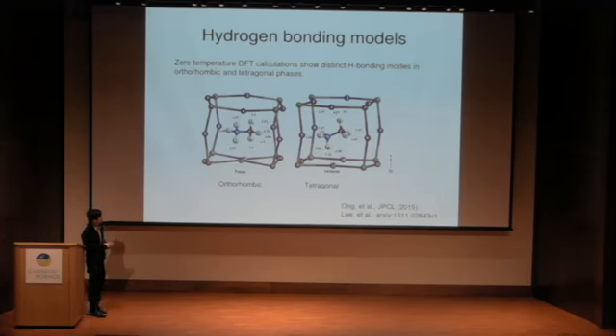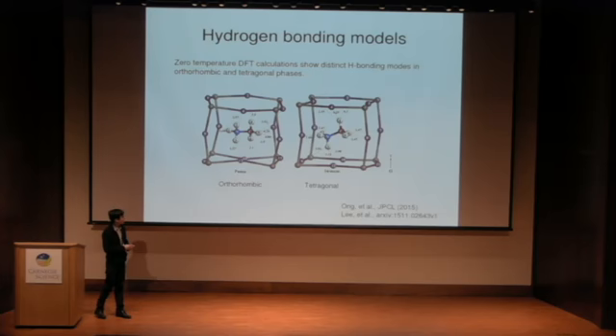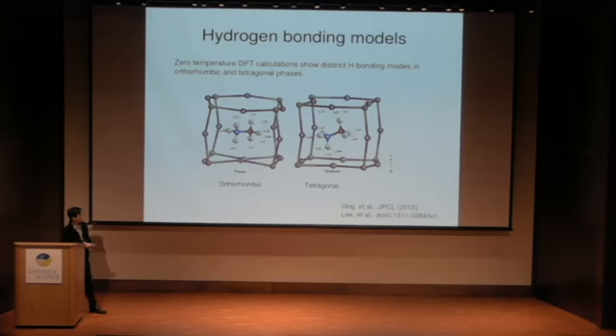Early DFT calculations proposed two types of modes of bonding of the molecule to the inorganic cage, corresponding to the orthorhombic and tetragonal structures having different types of hydrogen bonding. Basically, if you look carefully, you can see that the hydrogens are bonded to different halide sites in the two structures. But let me point out that these DFT calculations were done at zero temperature. And as we know, at higher temperature, the molecules can be rotating. So the picture is probably much more complicated than just two types of modes. But exactly how much more complicated?